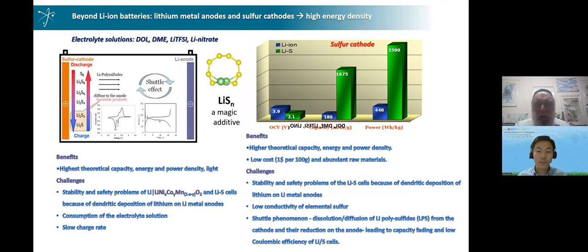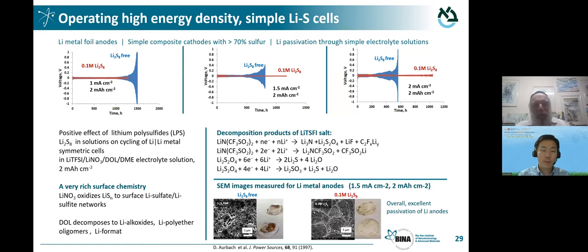I would say that with sulfur systems, by using a very simple additive, lithium sulfide, which anyway is being formed in the systems, but we use it a priori. From the beginning, we have lithium sulfide, and the electrolyte solution is dioxolane DME, lithium TFSI, and lithium nitrate. We have unique surface chemistry that avoids the famous shuttle effect simply because lithium nitrate oxidizes the sulfide and forms on the surface networks of lithium sulfur oxygen that enhance very pronouncedly the passivation of lithium. So we don't have the famous shuttle effect, and we demonstrate very nice stabilization of lithium. These are results from symmetrical cells.